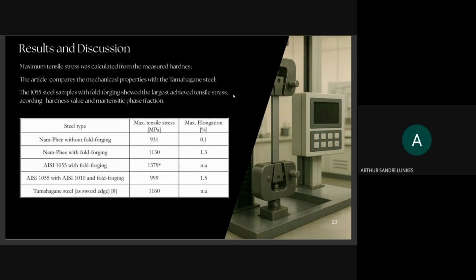Since the authors didn't get results for the AISI 1055, they used a mathematical approach to obtain the maximum tensile stress for the AISI 1055 with fold forging. The value they obtained is the highest value of all the steels here. He took the Tamahagane steel to make a comparison with the others, because this steel is utilized for the sword edge of samurai swords.